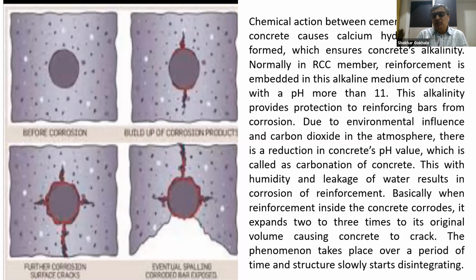Basically, when the reinforcement inside the concrete corrodes, it expands 2 to 3 times its original volume, causing the concrete to crack. The cover concrete gets cracked first because its thickness is less, and the phenomenon takes place over a period of time. This process may start from day one itself, but it will get expedited after 15 or 30 years, and then the disintegration of the structure starts.